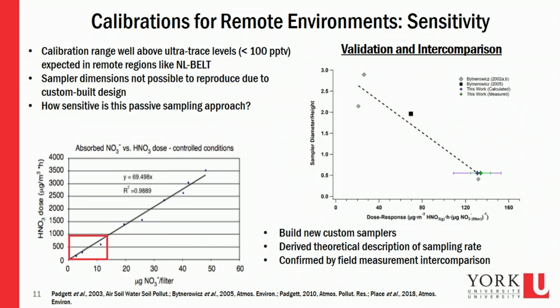What we actually surprised ourselves with a little bit was that we can use all the different samplers in the literature to come up with a pretty robust description of how these samplers work based on these nylon filters. If you know the diameter of the opening of your sampler and take its ratio to the height from the entrance of the sampler to where your nylon is located, there's a fairly good linear relationship that falls out of that that describes the dose response rate of your particular passive sampler. So we took all the different reports in the literature, came up with linear regression and approximated by calculation what we'd expect here in this blue point.